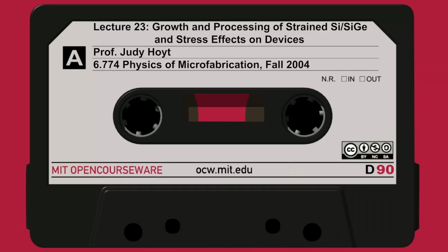For a strained N MOSFET, shown in blue, it goes up. And this enhancement factor, or the ratio between these two lines, stays about constant. In this plot, all the way down to about 90 nanometers or so was the shortest devices that were made, just around 100 nanometers. Since that time, shorter devices have been made. But the nice thing is that the enhancement doesn't seem to go away when you go to short channels. So that's very important for the technology.